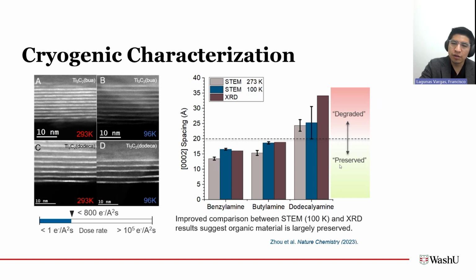So here I kind of draw a line where if we take a material that has a basal plane spacing below 20 angstroms, then we tend to be able to preserve it using cryogenic STEM. However, if the spacing is much larger, it's likely that vacuum effects, so the high vacuum in the column, will damage the material, or the material is just a lot more sensitive to the electron beam, where we still can't quite see the same spacings that we expect to see in XRD. So either the material is in this preserved region or it starts approaching this degraded region, even in cryo-STEM.